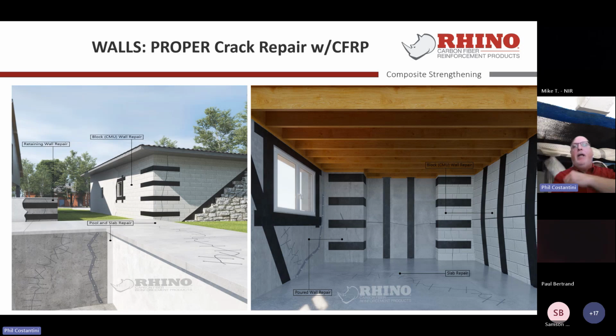Absolutely, yeah. And it just comes from my 30 years ago of concrete restoration repair, when I used to do it with epoxy bar. Even in a residential environment, mostly in commercial and warehouses, we'd show up with 15 or 20-foot lengths, and we cut them and bend them on site and drop them in there. We use the same nodule aspect, except the little nodules that are the end pieces of the carbon fiber are actually glass rod. So we get huge benefit of it. And then the smart asses that we were, we wrapped it in carbon fiber. So you get the strength of the nodule being glass fiber, and then the wrapping gives lateral support of a wall or primarily slabs, to prevent it from opening up again.